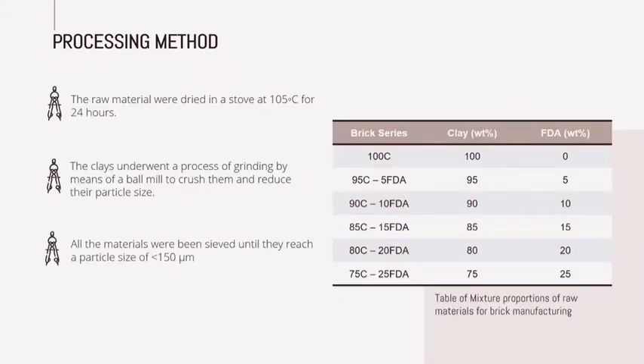For the processing method, the raw material was dried in a stove at 105 degrees Celsius for 24 hours. Then the clay underwent grinding by means of a ball mill to crush it and reduce its particle size. Both the clay and the FDA were sieved until they reached a particle size less than 150 micrometers. The different proportions of FDA waste were added to the clay.